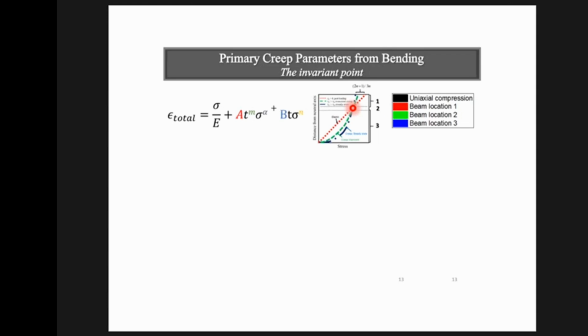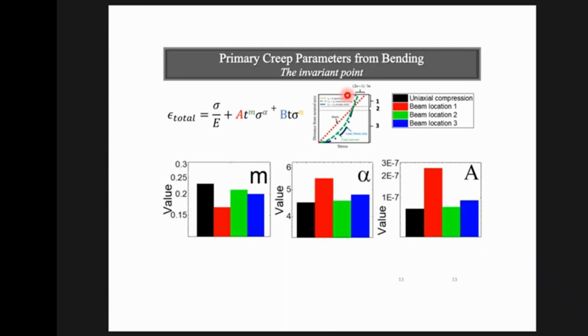If it were plasticity, it would depend on the relationship between stress and strain, which is the work hardening coefficient. So if you now monitor the stress at this point 2, which is roughly 2/3 of the distance from the neutral axis to the top surface, then you will find that you can recover all these exponents for, this is a representation of the total strain as elasticity plus the primary part and the steady state part. If you look at beam location 2, which is this green thing here, you'll find that you get a very good correspondence with the black uniaxial data, because the stress there effectively doesn't change.